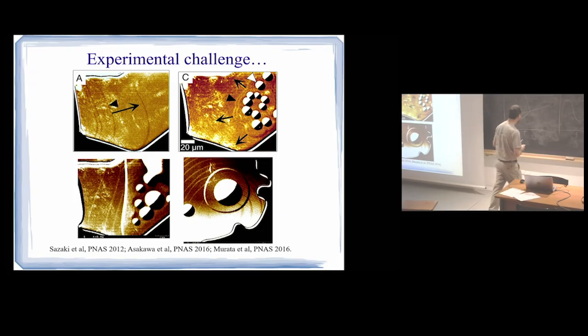What does that mean in a phase diagram? Where are we? Say we are at this temperature. It means we are a little bit above the sublimation line. And then ice starts being more stable than the vapor, and so the vapor deposits on the ice surface, and the ice surface grows.